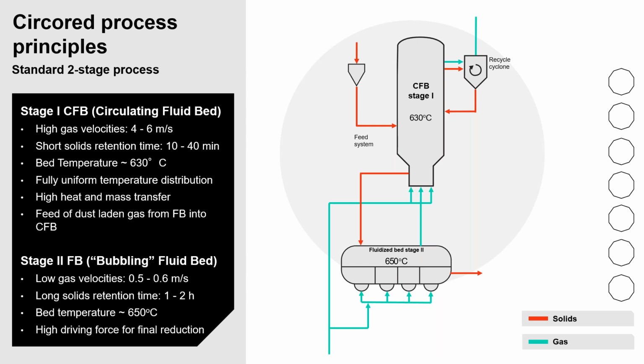For final metallization, the solid material is discharged to the FB reactor, giving it the required residence time and a high thermodynamic driving force via the fresh and hot hydrogen to reach metallization degrees above 93%. The overall reactor setup is mimicking a countercurrent process to harvest its thermodynamic benefits.